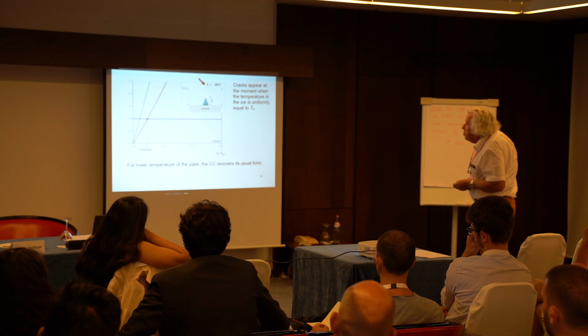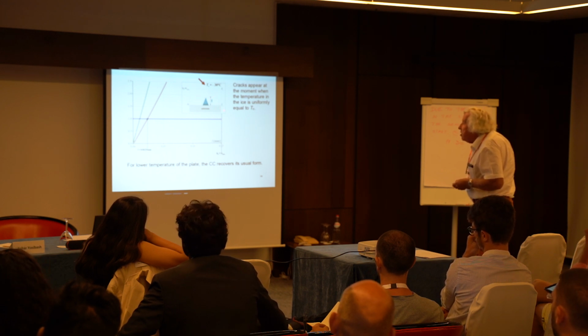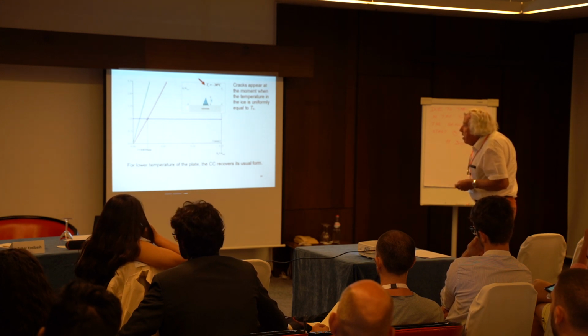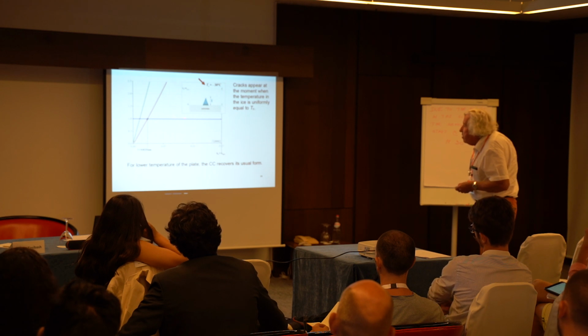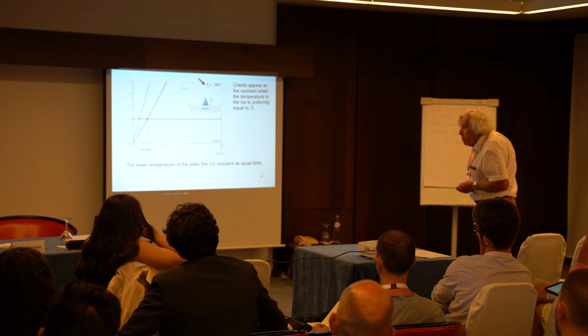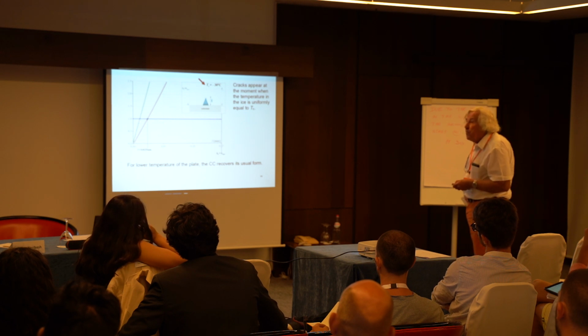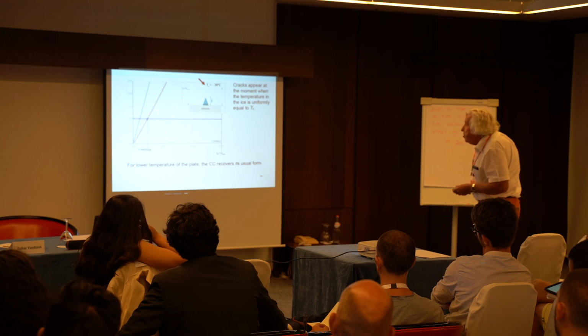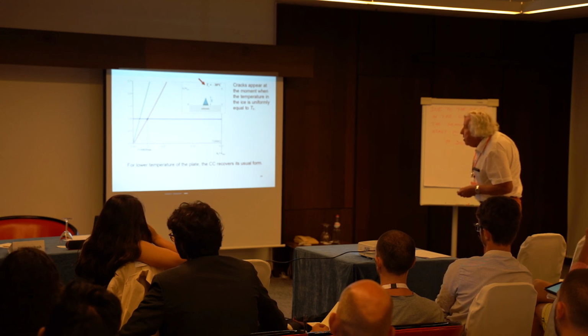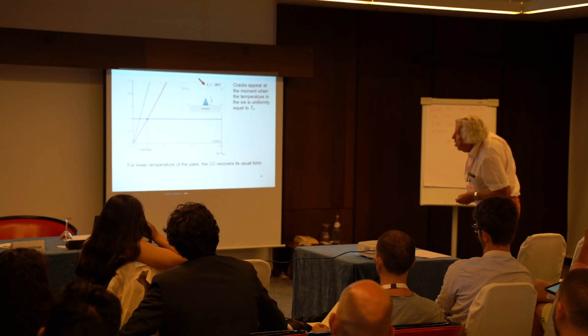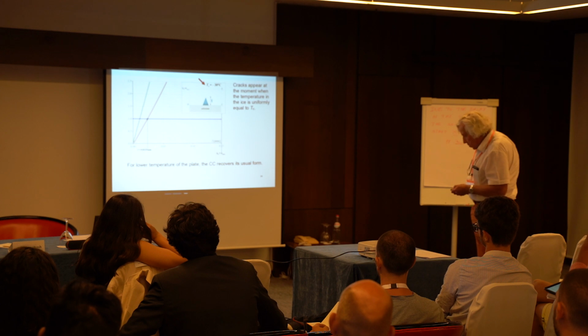Now we wait a long time, and then at minus 30 degrees Celsius, the water has turned completely to ice, and the temperature now is homogeneous through the thickness of the ice layer. It means that the stress condition is fulfilled. This is the energy condition, and this gives us the solution for this case. Okay, with a rather small crack spacing.